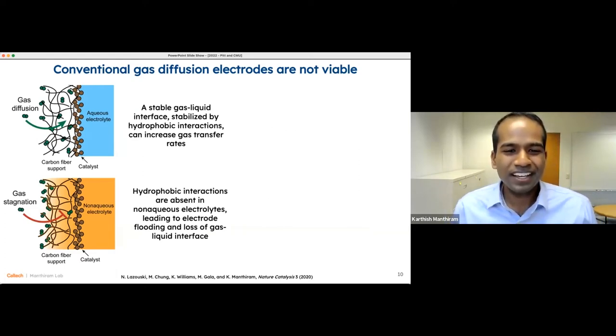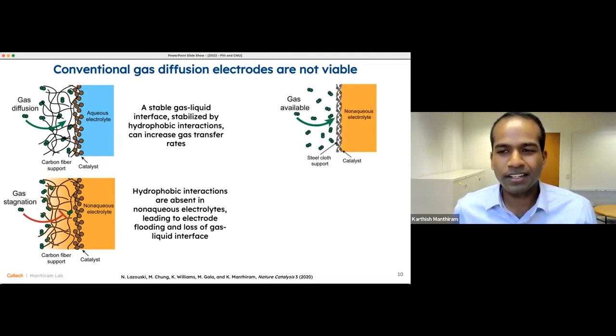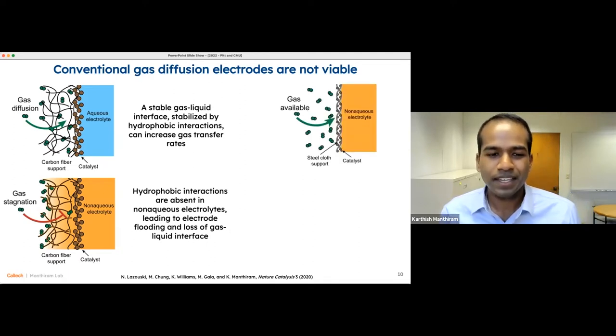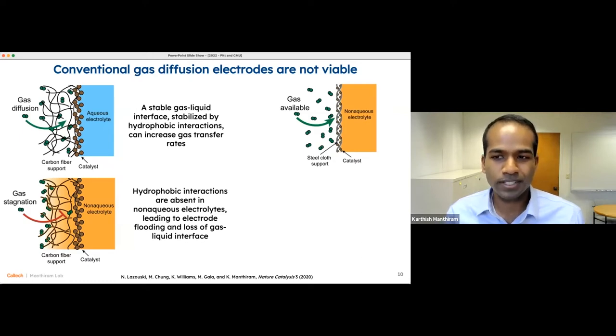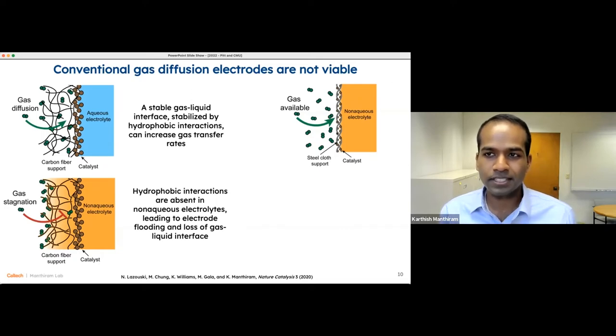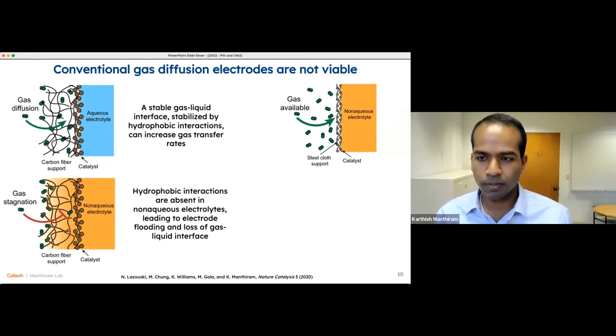So one can see here that there is a challenge in wetting, and the way to overcome this is to use a different material that is porous. And so we've exchanged now a carbon fiber-based support for one that is based on stainless steel. The stainless steel cloth is not as easily wet by the non-aqueous electrolyte as our carbon fibers. So this leads to a degree of prevention of flooding of the stainless steel cloth support. We also apply a very small pressure across this stainless steel cloth, which allows us to maintain this boundary, as I'll show in a moment.